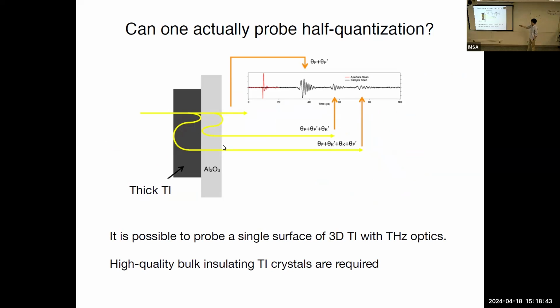So think of a thick single crystal of topological insulator, let's say bismuth selenide, and a normal dielectric substrate, which is required in this case. If we do the measurement which I showed earlier, just send the light through and measure the rotation of this pulse, you'll see the Faraday rotation on this surface, which is top, plus the Faraday rotation on this surface, which is bottom. But at the end of the day, it's still summing up to an integer, not a half integer.